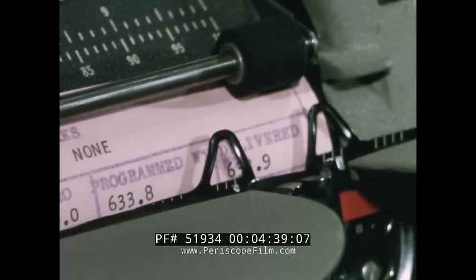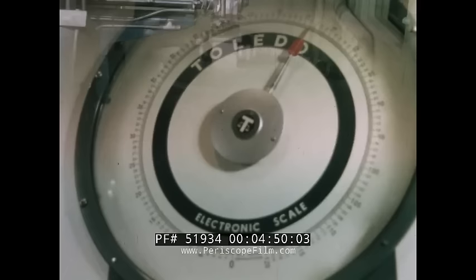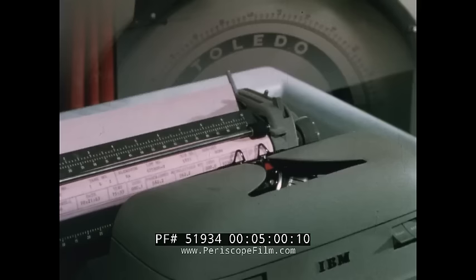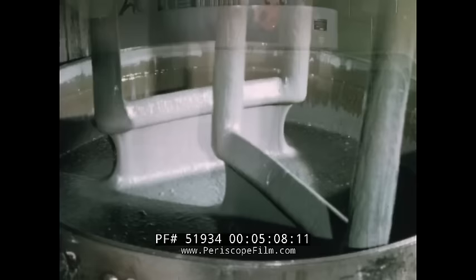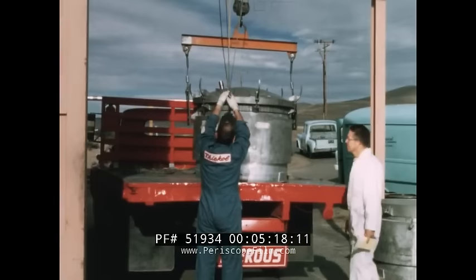Now, an automatic advancement to aluminum, which is also weighed into the premix can. The small amount of powder in suspension is considered at final cutoff. The weight of aluminum is checked for accuracy against program tolerance. If sufficiently accurate, it is recorded. Aluminum and polymer are blended thoroughly. Sealing avoids contamination. Formula number and batch characteristics follow the premix container to the final mix building.